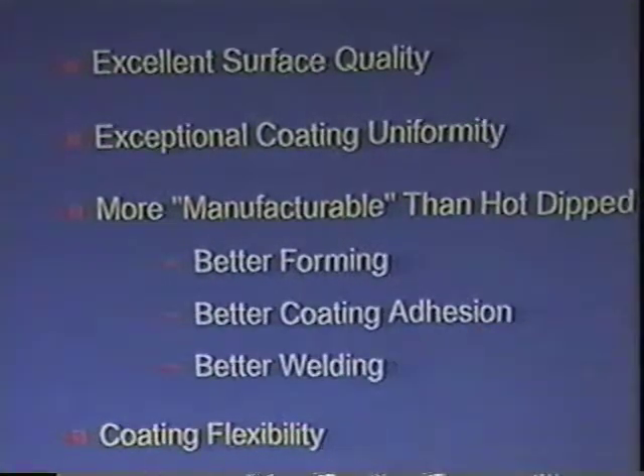So yes, excellent surface quality, especially as opposed to galvanized. You saw the galvanized, just basically molten zinc on top of steel. This is electroplated, so it has a much better chance of making that good surface. Exceptional coating uniformity. I wouldn't say exceptional. Electrogalvanized is a more uniform coating than hot dip galvanized. And especially 10, 15 years ago, it was an exceptionally better coating as far as uniformity across the strip.